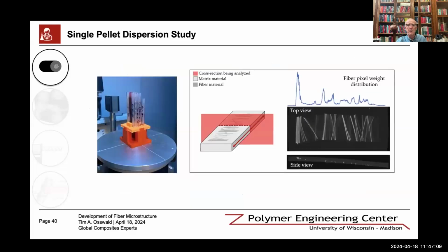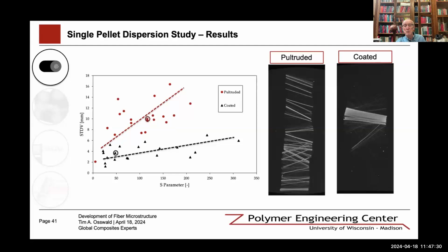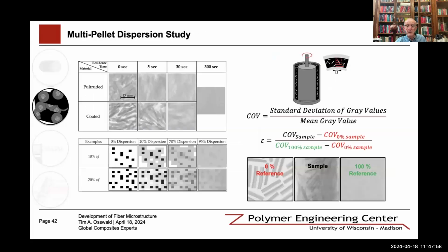And so we did a lot of micro CT analysis on the dispersion of the fibers using sliding plate rheometry, and using micro CT was found to be a great way to assess the dispersion of the fibers. So we can see the pultruded versus the coated ones, the standard deviation of the difference in the color of the pixels determines how the fiber that is either coated or pultruded behaves differently from one another, to be able to include that in our models.